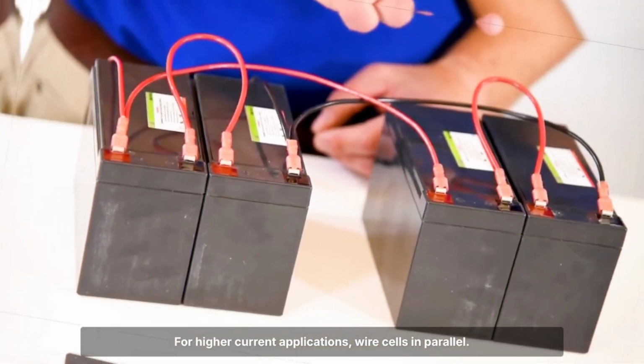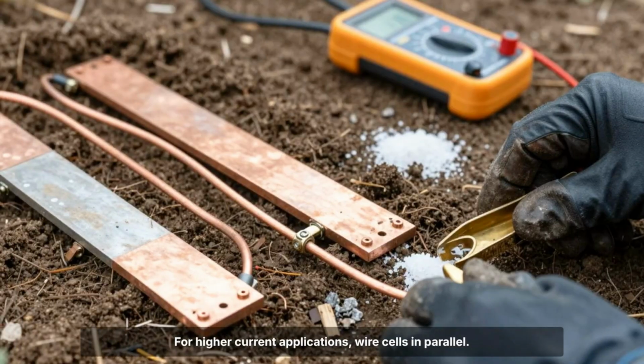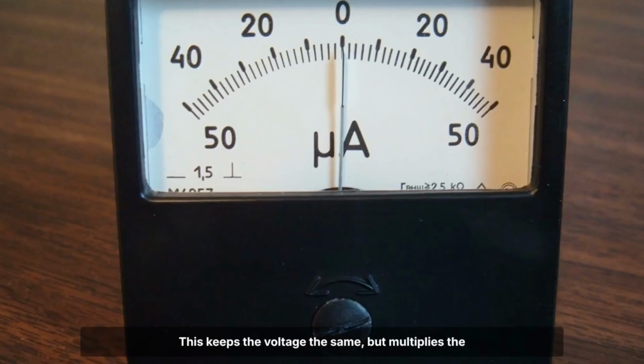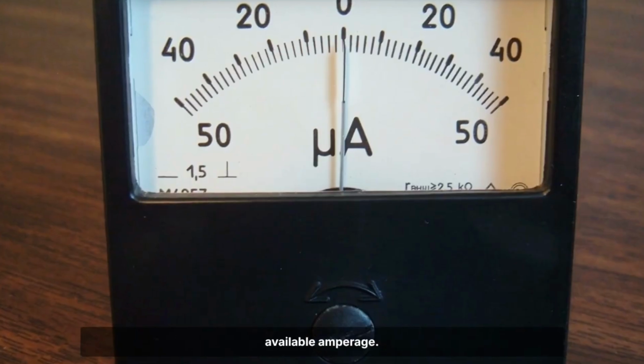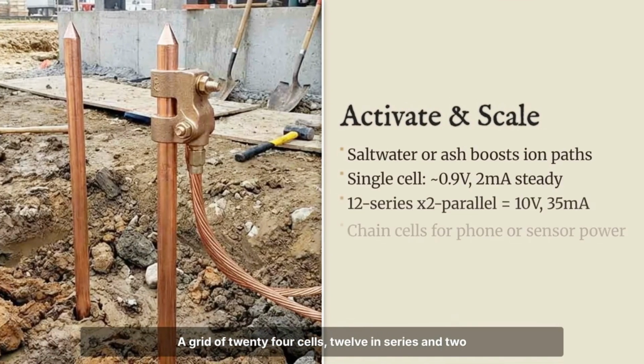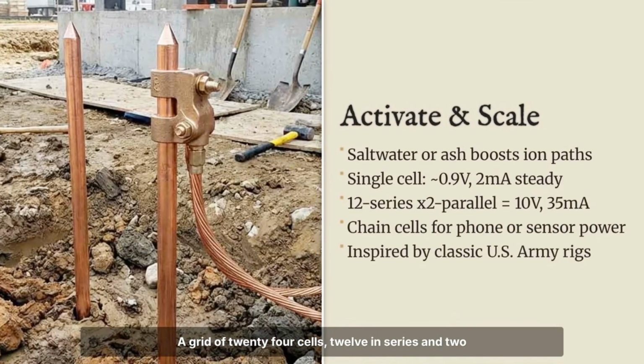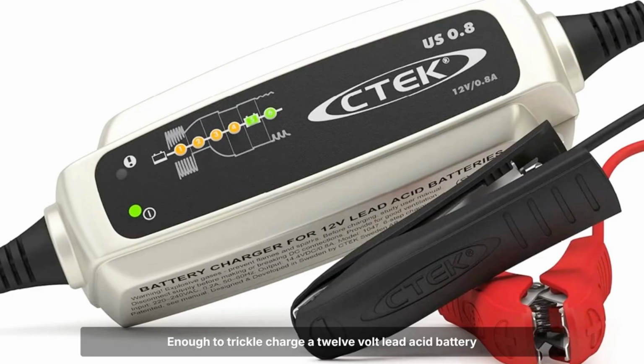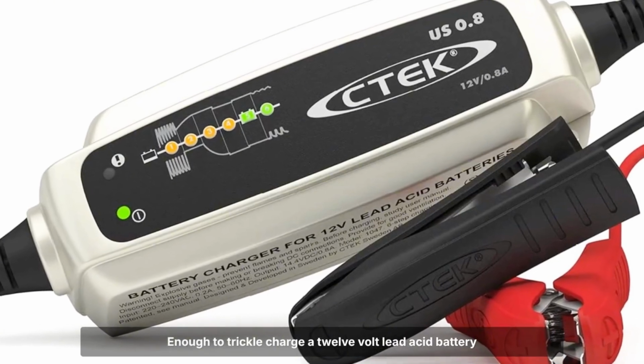For higher current applications, wire cells in parallel. This keeps the voltage the same but multiplies the available amperage. A grid of 24 cells, 12 in series and 2 parallel strings, produces approximately 10 volts at 30 to 40 milliamps, enough to trickle charge a 12-volt lead-acid battery overnight.